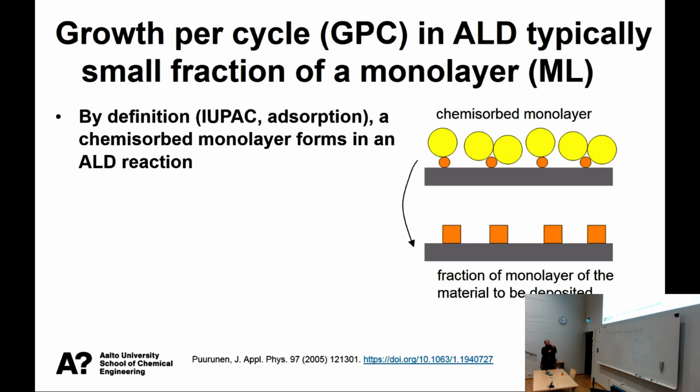So typically we have a metal atom or ion that is carried to the surface with ligands that are actually bigger than the metal itself. And at least in some cases, it's the steric hindrance by these ligands that causes the reaction to stop. The surface is full.